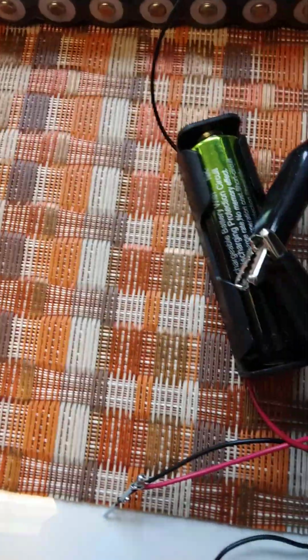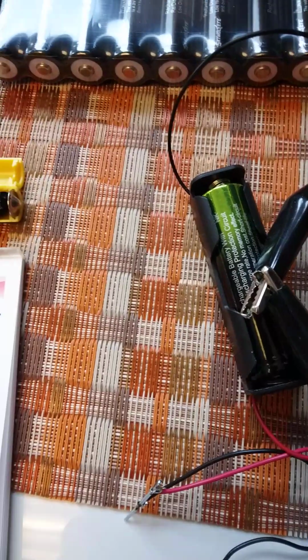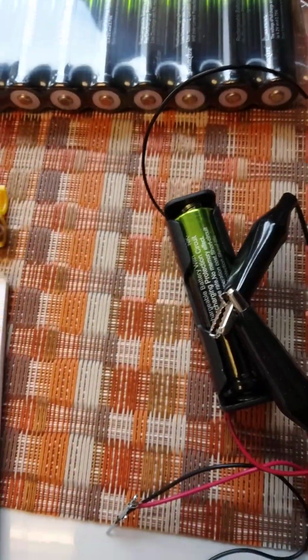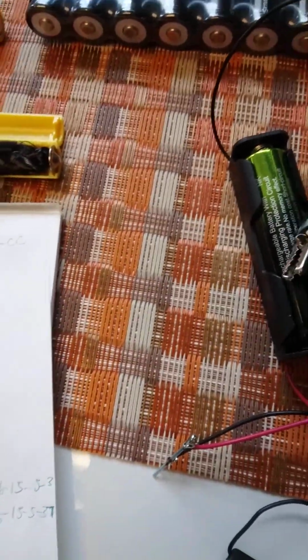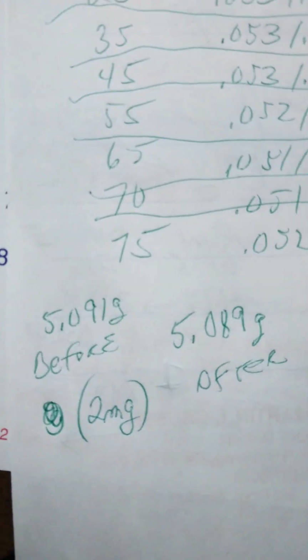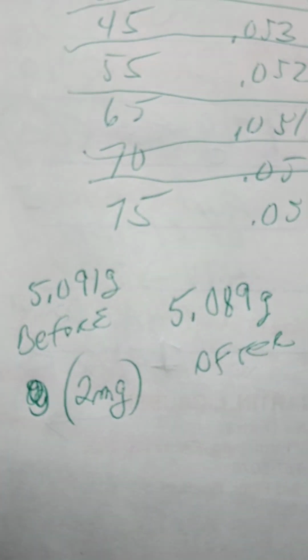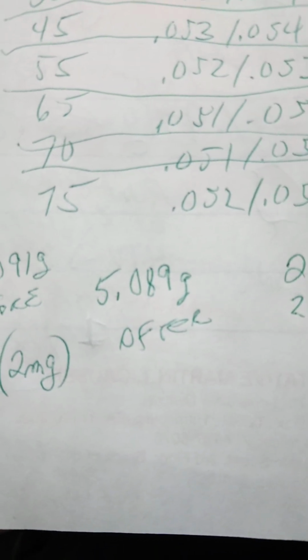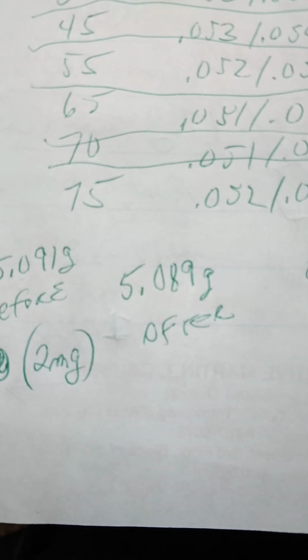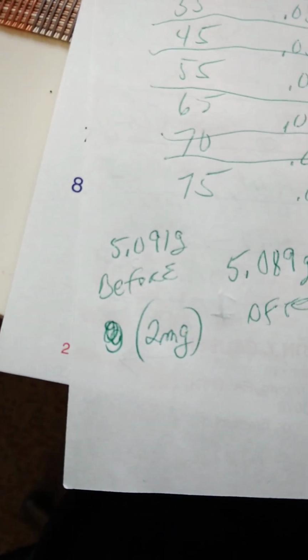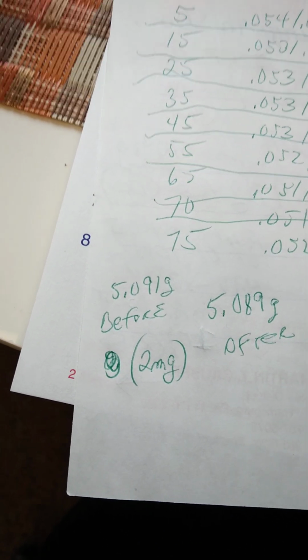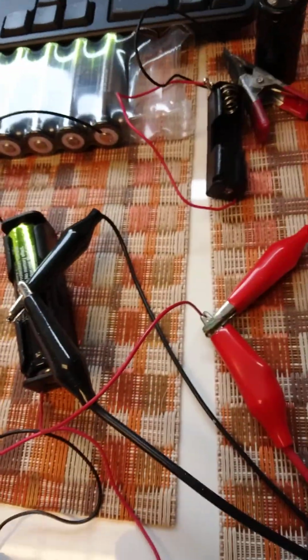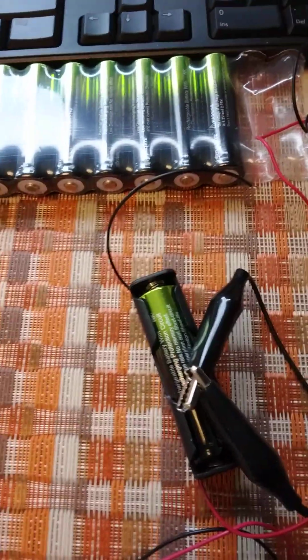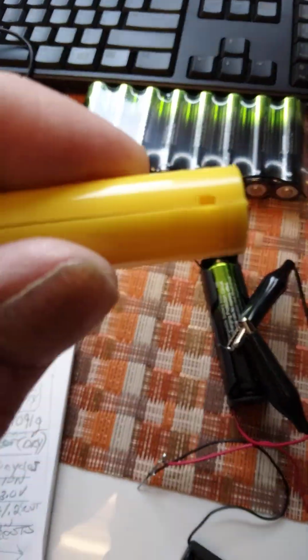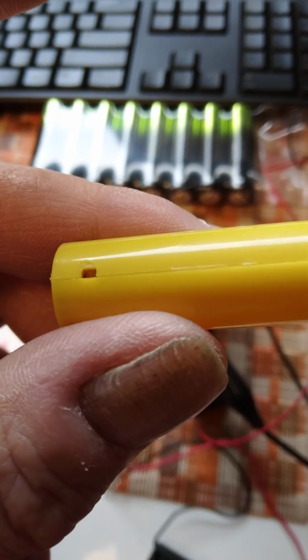After 75 runs, the unit with the yarn was 5.091 grams, and after 75 cycles of charge-discharge, 5.089, so I lost, if my math is correct, 2 milligrams. Not completely sealed. There are small vents. As you can see, there's one, and there's the other.